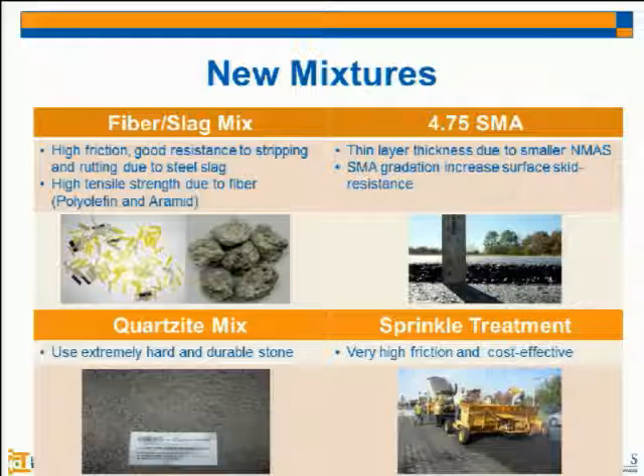4.75 SMA. But as I mentioned before, some states developed the 4.75 dense graded mix. The problem of this 4.75 dense graded mix is that the surface is too smooth, so friction is always an issue on those mixtures. So we selected the 4.75 nominal maximum aggregate size, but designed this to be an SMA gradation, to have a relatively rough surface.